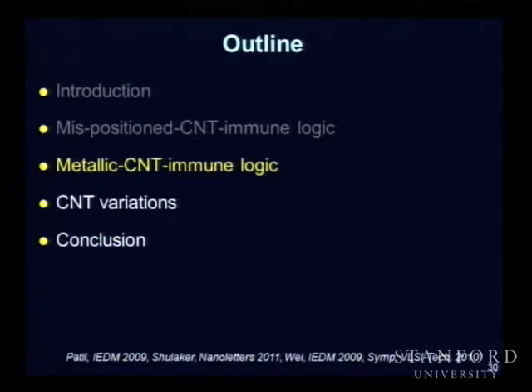Yes? On the picture you showed for a gate, several nanotubes in parallel. Yes. Why? Because what happens is that when you have a quartz substrate, and this is very well known in the material science literature, when you grow carbon nanotubes, the carbon nanotubes actually follow the crystal structure of quartz, and that's why you get these highly aligned carbon nanotubes along the crystal structure, versus when you have a silicon substrate, the carbon nanotubes just grow everywhere like a bowl of noodles.